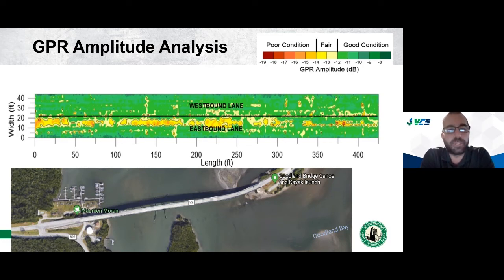We're obviously seeing moisture and chloride exposure. There may be active corrosion. There may be delaminations. Now, I'd want to look further into these areas, and I would use GPR to focus. Maybe I'd look at this large yellow spot to the left near 0, maybe this really hot spot at 375, and maybe this large yellow area around the center at 225. I'd use GPR to do some further investigation work in those areas, but I cannot get quantities of delaminations from this. And I think that's an important aspect to understand of GPR.